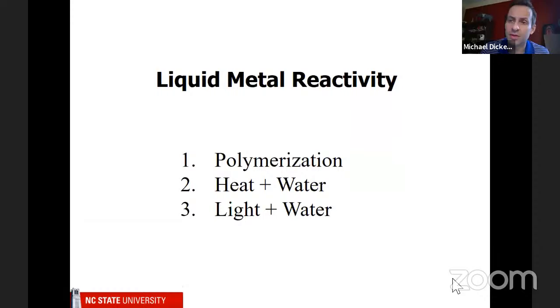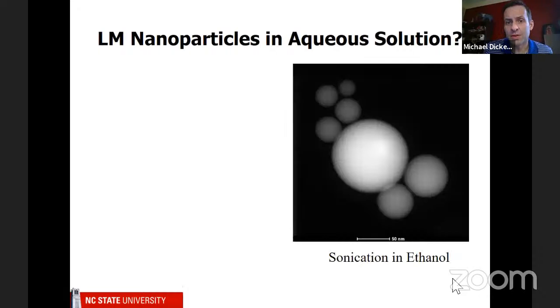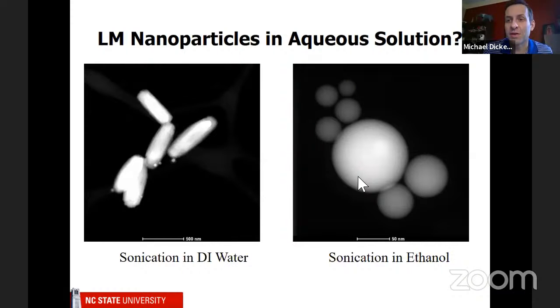Another one is actually sort of good and bad. Gallium behaves a little bit differently in water. And so what I've shown you up till now is basically sonication in something like ethanol or other liquids, and we just form particles, and they look nice, but they're kind of boring. Well, we tried to do this in water, and it was very surprising because instead of getting spheres, we got rods. And it's a liquid, so we kind of thought it should form spheres. So we did some experiments. We weren't sure if these were because of sonication or some other effect.